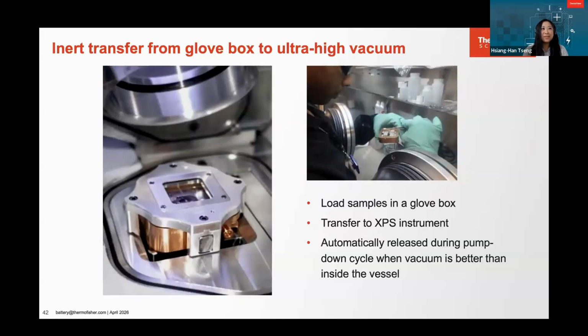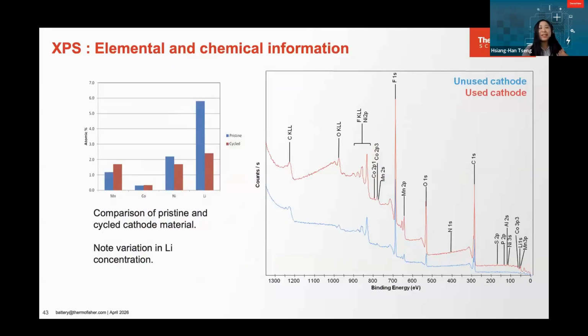Next slide, please. During the XPS, once the samples are in the system, the first thing that we would do is take the survey scans, because this is where we start seeing what elements are present in the surface of our sample. This is just an example that shows two samples, pristine and used cathode materials, being analyzed with the XPS.